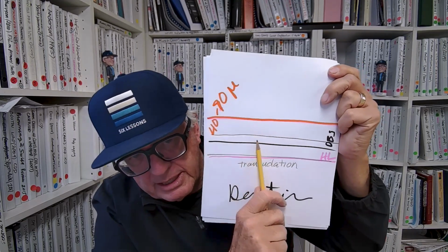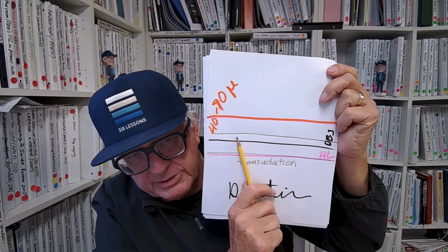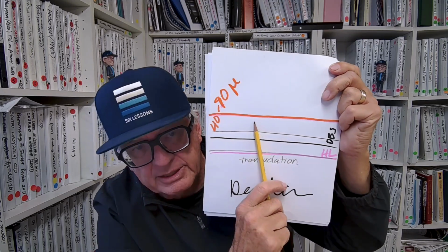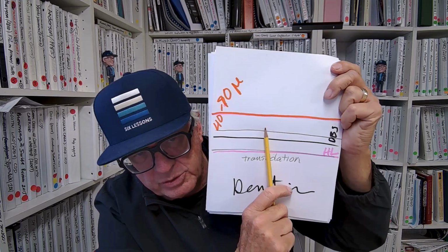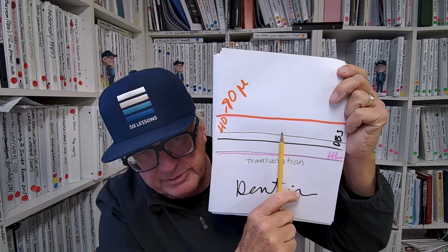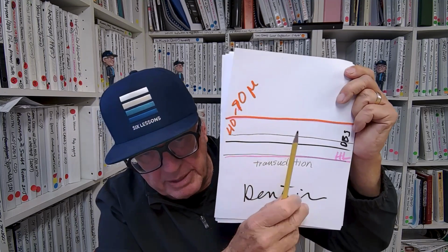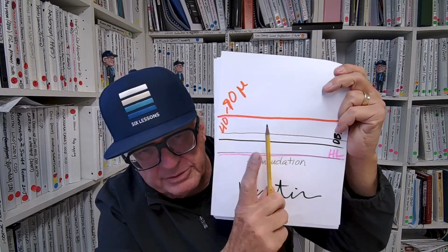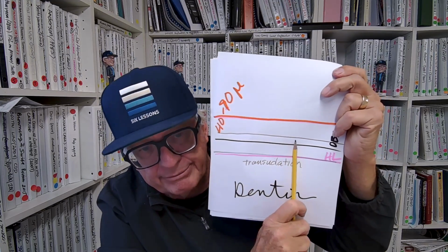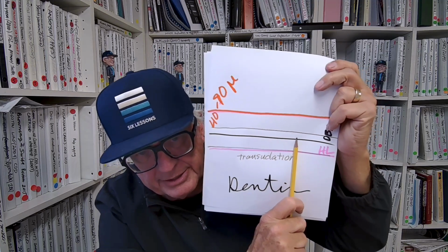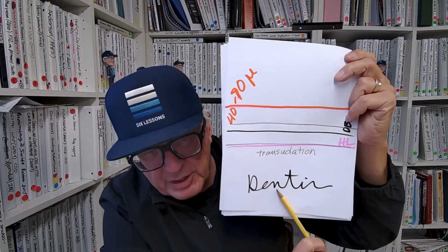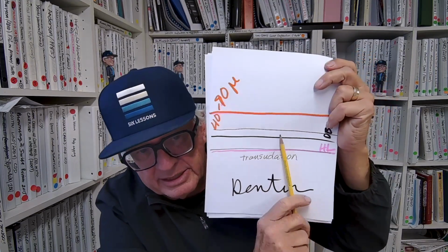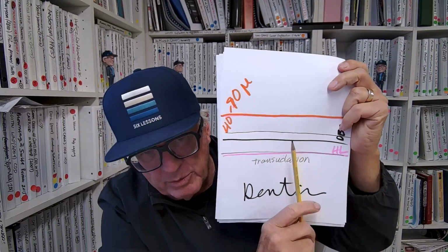And the only time this 10 microns will polymerize is when another layer of at least another 10 or 15 microns is placed, but usually it's a layer of restorative composite, which would be 500 microns of flowable, or 2000 microns if you put 2 millimeters of a composite on top of it. But you have this trapped, unpolymerized, pulpal fluid-filled layer that if you start biting on this restoration, now that goes back into the pulp. It hurts. You can't bite on it. This is the experience that I had with Photobond.